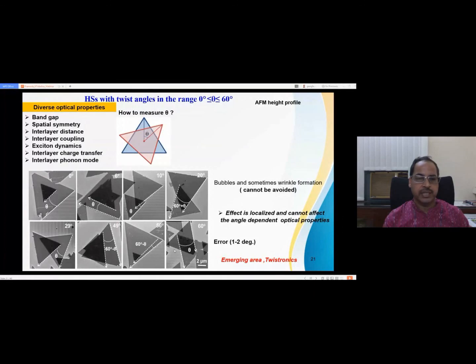Okay, so this is my heterostructure. I rotate the angle between 0 to 60 degrees. You can see here, this is 0 degree. This bottom layer is called MoS2, and this is the WS2 layer. I rotate this one using the pickup transfer technique. So you can see different diverse heterostructures here. And you can see the AFM image. Here the bottom layer is MoS2, and this is one typical AFM image I am showing. Top layer is WS2.